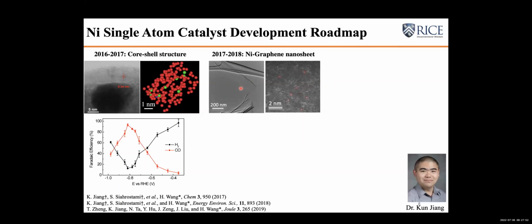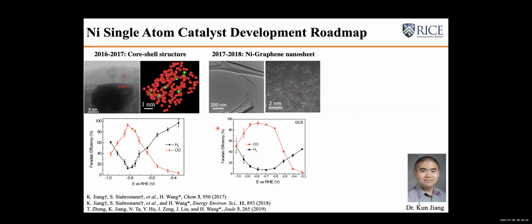And during which, by controlling the amount, you won't result in any particle or cluster formation, which can be easily detected by X-ray absorption spectroscopy. So in this case, we further demonstrate the high performance of nickel single atomic sites, with selectivity over 90% and an even wider electrochemical window.